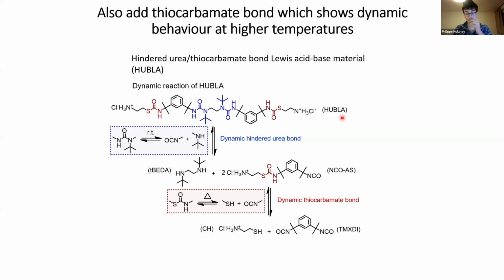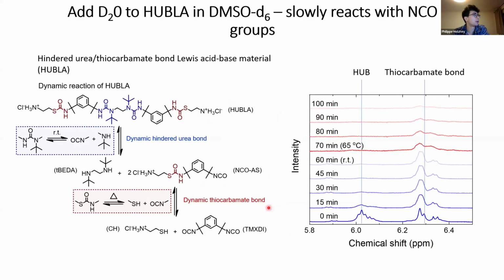And now the big idea we had is that with increasing temperature, we also want to have some form of healing. And that's why we have this thiocarbamate bond, which shows a higher reactivity at higher temperatures, which we added. So this is the molecule, the HUBLA. This is the hub. And then we also have a thiocarbamate bond here. And the combination of both allows us to have sort of a dynamic covalent bonding under heat and moisture. And we also measured that.